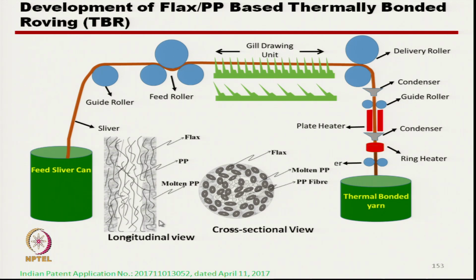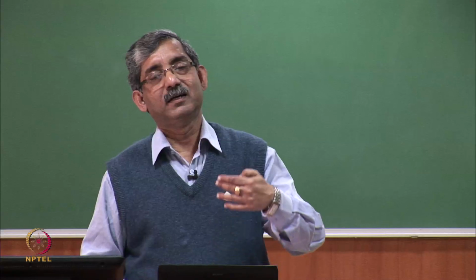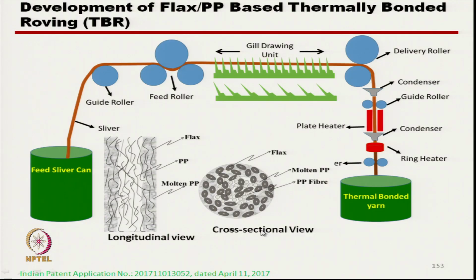Here we can see that polypropylene fibers at the surface of the yarn are melted, and the polypropylene fibers in the core are still in the staple fiber form. So, there is partial melting, which helps in retaining flexibility. At the same time, due to melting, the strength of the strand, that is the roving, is such that it can sustain a certain load. This is the cross section, where these are the flax fibers and here are the polypropylene.